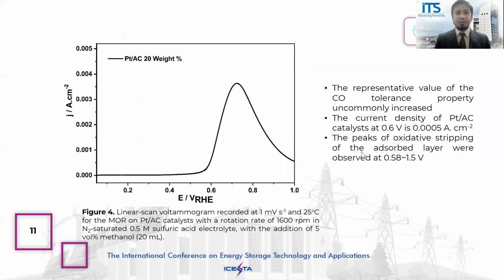Also, we performed the methanol oxidation reaction using linear scan voltammetry at 1 millivolt per second and a rotation of 1600 rpm. The representative value of CO tolerance property increased, and the current density of the carbon supported Pt catalyst at 0.6 volt is 0.0005 ampere per square centimeter. The peak of oxidative stripping of the adsorbed layer was observed around 0.5 volt.